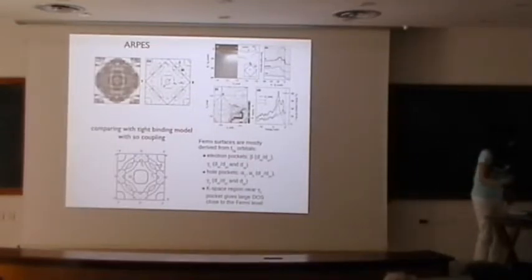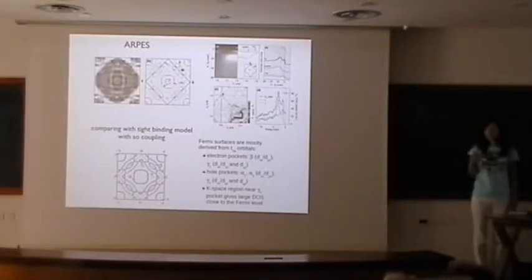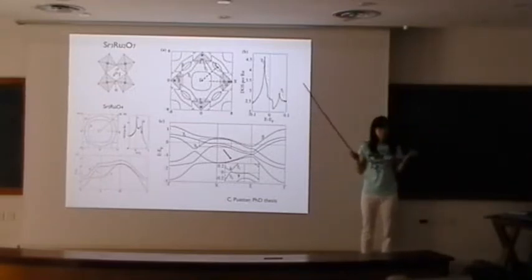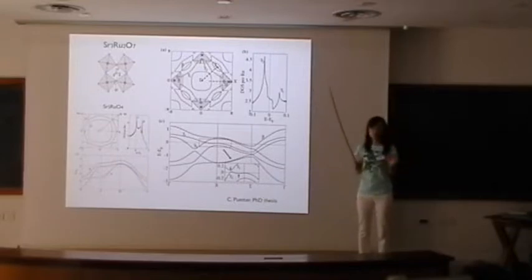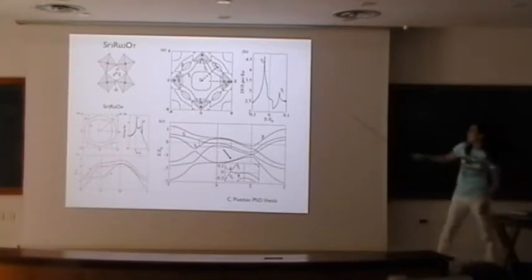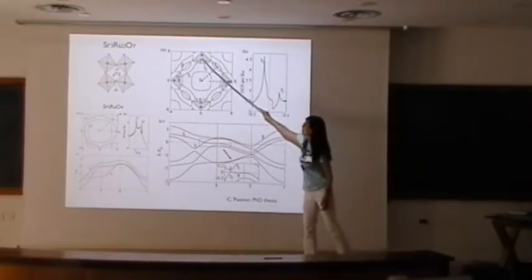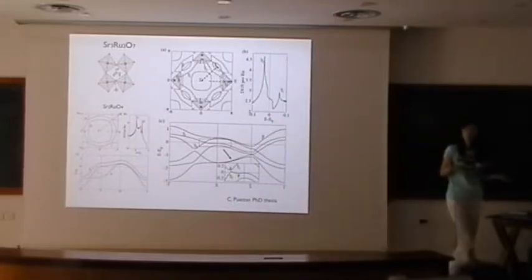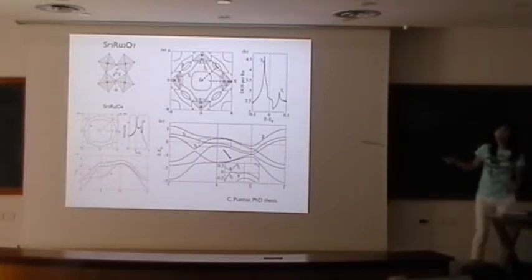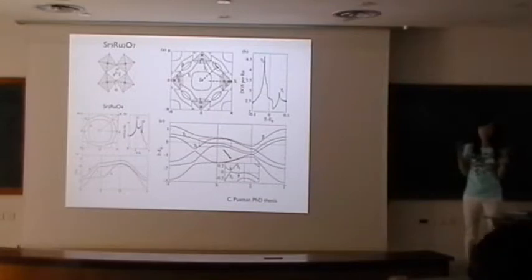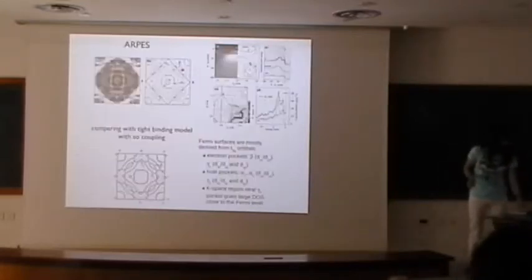But what's important for the nematicity, remember that this is related to the band singularity. And in weak coupling, that's in some sense a trivial statement, because I have a lot of density of states at a certain Fermi surface right here, by the Fermi level. I have so many electrons in that state. So even a small interaction would become so efficient to form some kind of Fermi surface instability. So it's important that you recognize that gamma 2, which is this little pocket, and gamma 1, which is nearby, mostly coming from these edges, has the strong logarithmic Fermi singularity. So the toy model that we have learned can also apply here. It's just that it has a little bit more sophisticated or more realistic band structure and orbitals involved.